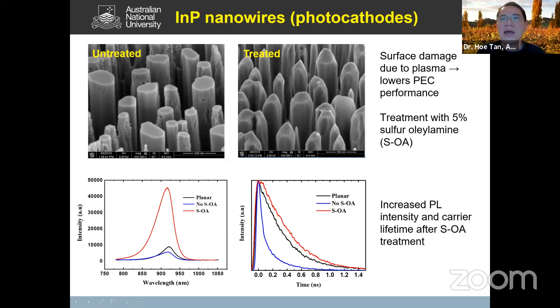And we also did time-resolved measurement. You can see after the oleylamine treatment, the lifetime is significantly longer. Again, all these points show an improvement in the quality of the material.